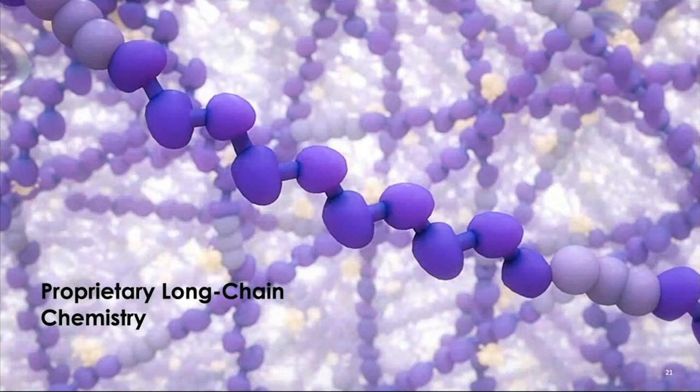What is this resin? It has the same chemistry we've known and loved — a highly reinforced composite resin material — but with some new tricks. Because it is cured not by a curing light in the mouth but by a machine, and particularly it is cured in very small increments, we're able to get a higher degree of cross-linking of the polymer. We have this long-chain chemistry, a new oligomer developed that is able to cross-link at an alarming rate compared to direct resins in the mouth.